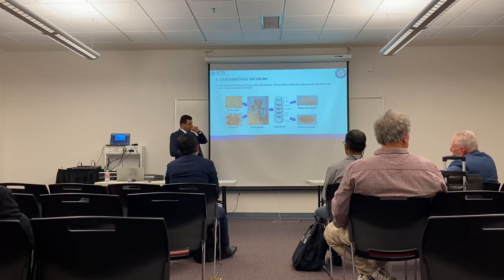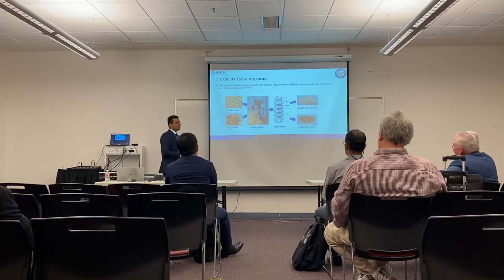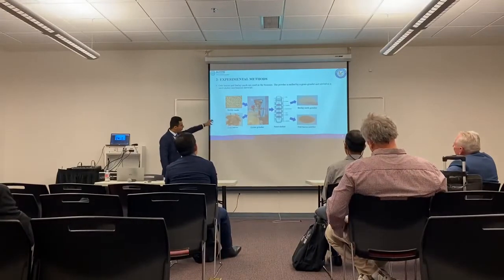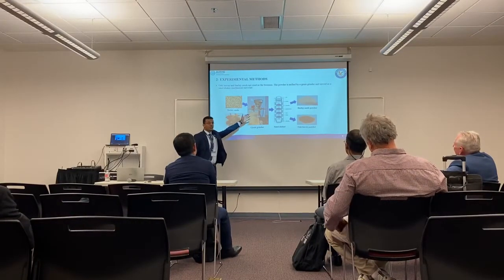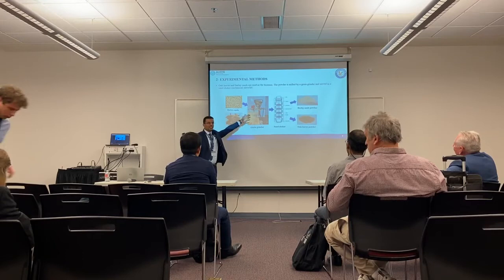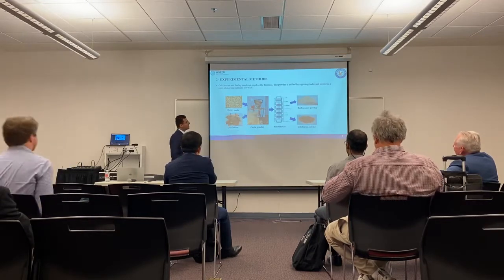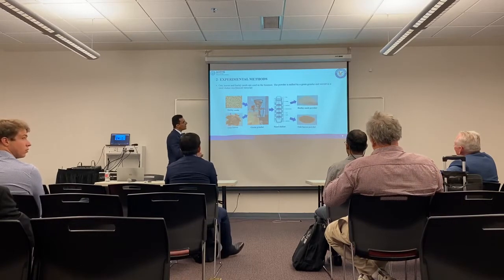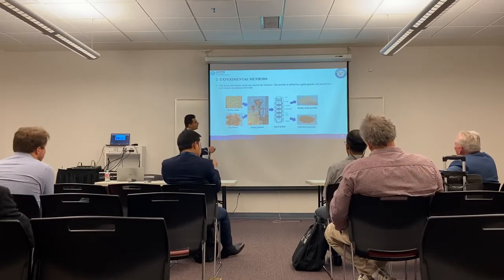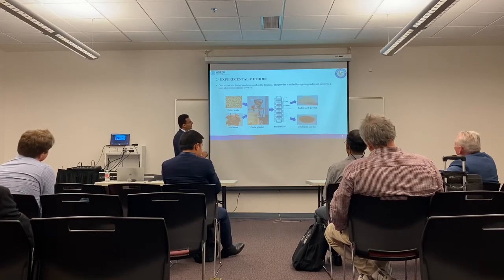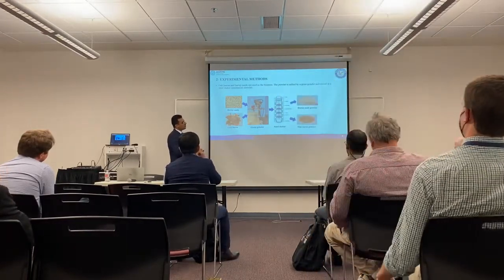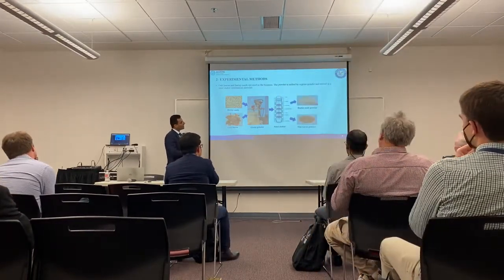Our experimental methods. For example, we have two biomass materials. This image is for barley seeds, and this is for oak leaf. For example, we took these barley seeds and crushed them in the chemical grain grinder. Then we sieved it in the sieve shaker to prevent coarse particles. Then after that, we got two powders. This is barley seeds powder, and this is oak leaf powder.